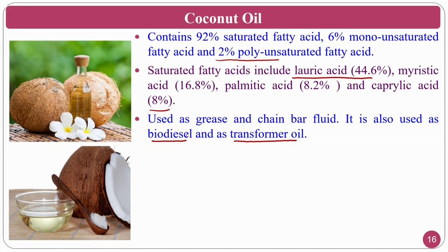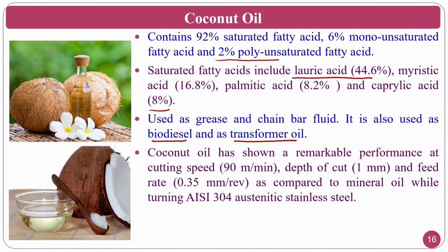If it is biodiesel, that means its emissions will be tested by the thermal engineers. So, we should not worry much about the emissions of this one. So, we can directly use this. As I said, some of the people even consume the coconut oil inside the body; it is biodegradable and all those things. Coconut oil has shown remarkable performance at a cutting speed of 90 meters per minute, depth of cut 1 mm and feed, okay, compared to the mineral oil.